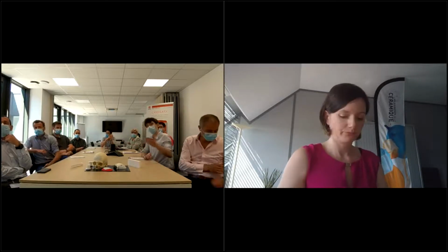We have a question about surface roughness of the parts. To give you a rough idea, after sintering and without any post-treatment, it is between 1 and 2 micrometers. We are sometimes using tumbling, a method of polishing, and we achieve between 0.1 and 0.2 microns.